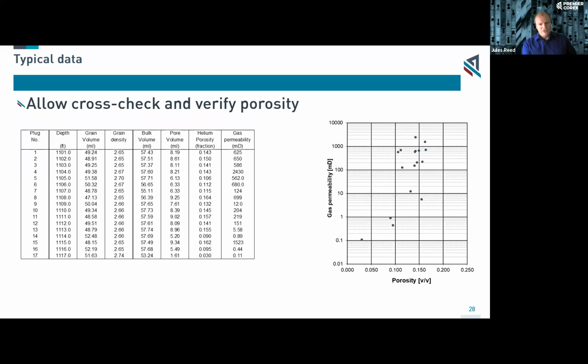We might get grain volume and bulk volume, pore volumes. The grain volume and bulk volume help us to understand the porosity data. And we can make our own calculations and check that we agree with the porosity, and we find that these are reasonable. So the data on the right stands as it is.